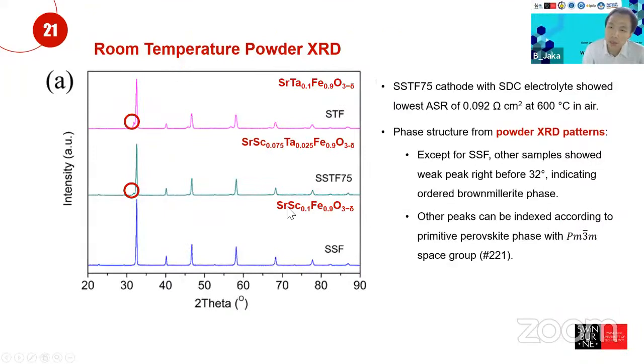The first thing that we did is we compare the structure of the co-doped one. In this particular scenario, we are only interested in the one that we doped, where the tantalum is only 0.025 and the scandium is 0.075. We compare it with where only scandium exists at 0.1 on the B side, and only Ta at 0.1 on the B side. So the SSTF 75 in here shows the lowest ASR of 0.092 at 600 degrees Celsius.